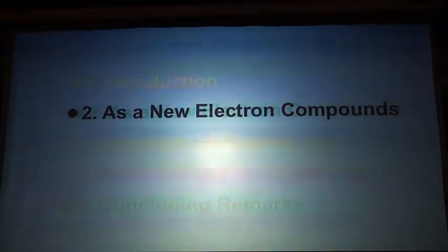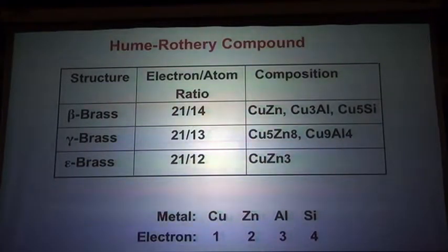And now I come to the second part. This has a very close relation to metallurgy, because I use the principles of metallurgy so that we can design new alloys which have the structure of quasicrystals. And probably most people here know very well that there are three criteria in the Hume-Rothery rules. First is the atomic size factor, the second one is electronegativity, and the third one is the e/a rule.